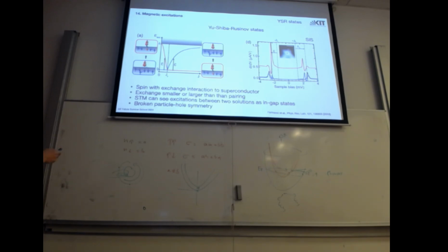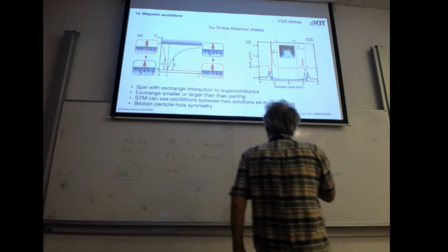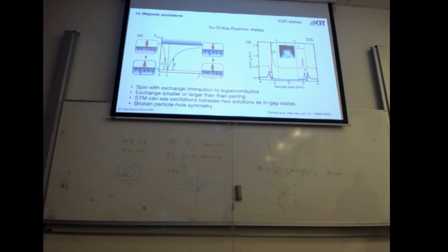And if I tunnel into this object here, I can excite the system from the ground state to the excited state. Let's say the exchange is small, the ground state is this, and there's an excited state. I break the Cooper pair, it costs me delta, but I gain the exchange J, but it's smaller, so this is an excited state. Or if I tune J, actually the order of the state energies is opposite. I can go from the ground state, the large J exchange, antiferromagnetic alignment, to the excited state, the unbroken Cooper pair. So there's an energy with which you can excite between those two. This excitation energy is smaller than the superconducting gap. You can live inside the gap.